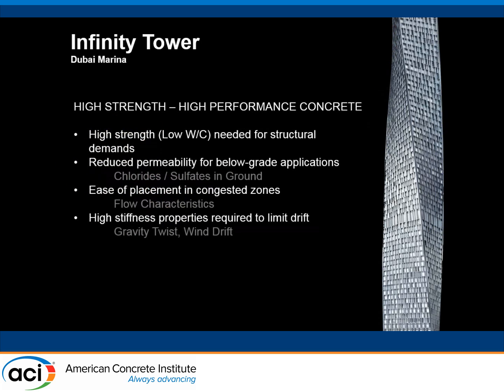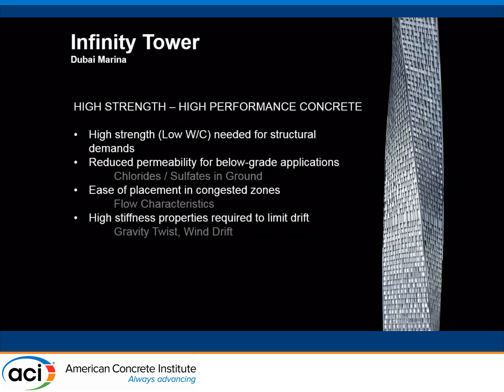For Infinity Tower, the motivation to do high-strength, high-performance concrete was for a couple of reasons. Certainly, we wanted the high strength and low water cement ratio for the structural advantage of keeping members as small as possible to maximize the amount of sellable area. We also were looking at trying to achieve reduced permeability for the below-grade applications because the chlorides and sulfates in the ground in Dubai are pretty extreme. And then you'll see in some of my construction photos, we've got quite a bit of congestion in some zones, certainly at the lower part of the building. And so we wanted to maximize the ease of placement and improve the flow characteristics of the concrete.